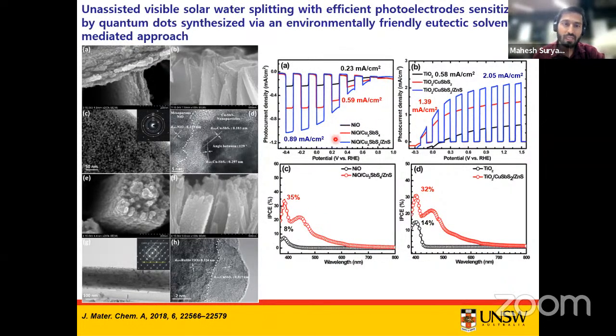So these are simply LSV measurements from where you can understand there's an improvement in the photocurrent density after sensitization of the NiO and the TiO2 with these copper chalcogenide compounds or nanoparticles. Not going to explain the value improvements, because it can simply be seen from these plots.